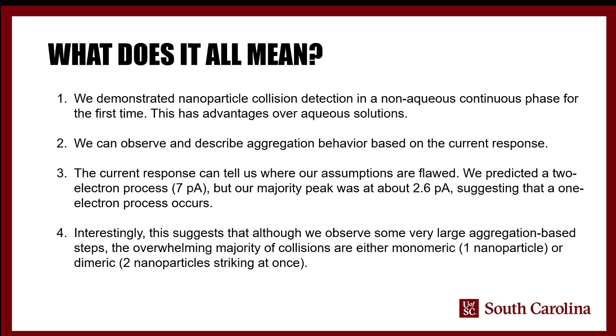So kind of going back to what does it all mean, like I said, we demonstrated nanoparticle collision detection in a non-aqueous continuous phase for the first time, and this has some advantages over aqueous solutions. A couple of things. One, it opens up this detection strategy to molecules and chemicals that are not soluble in water. But it also, non-aqueous solvents in general have much wider electrochemical windows.